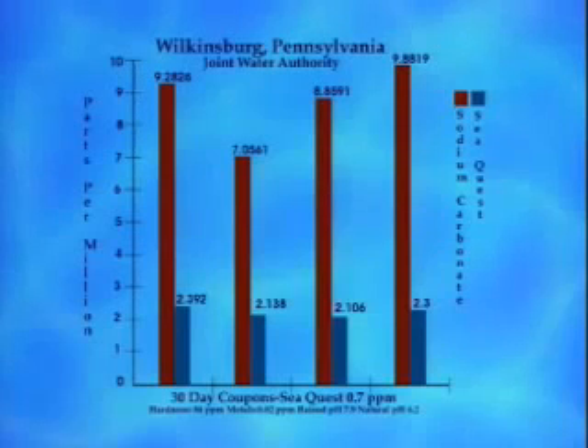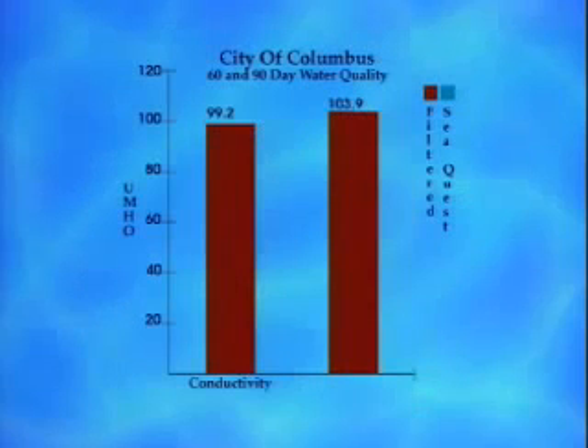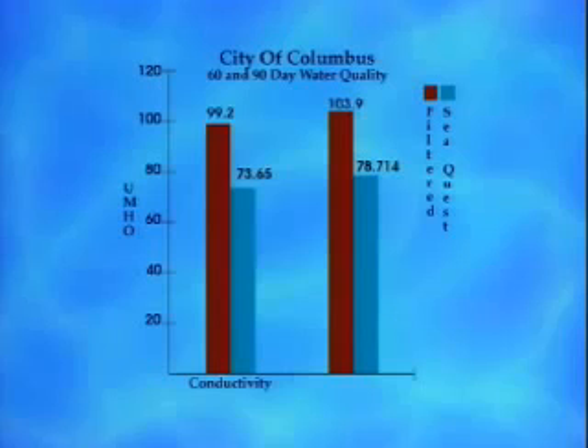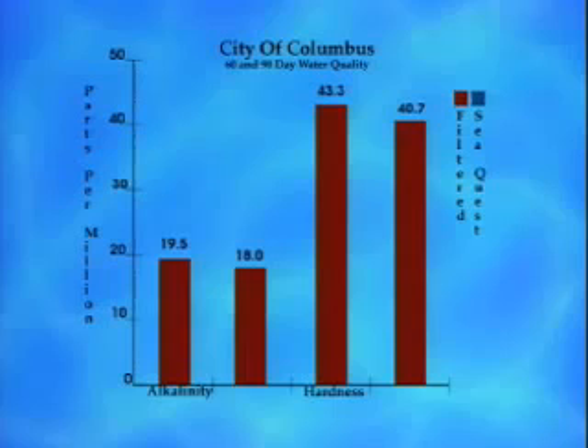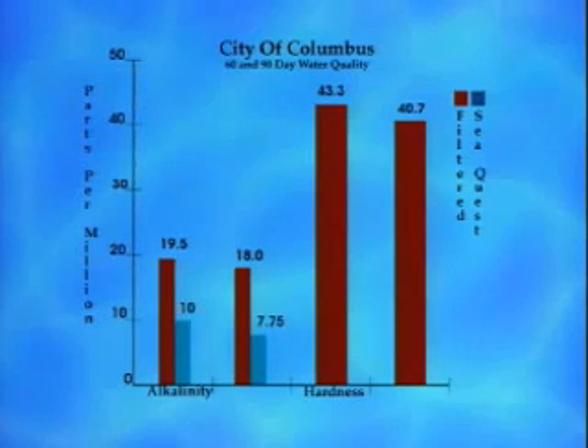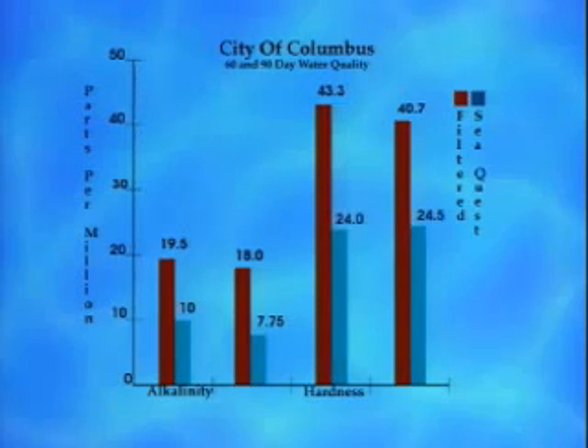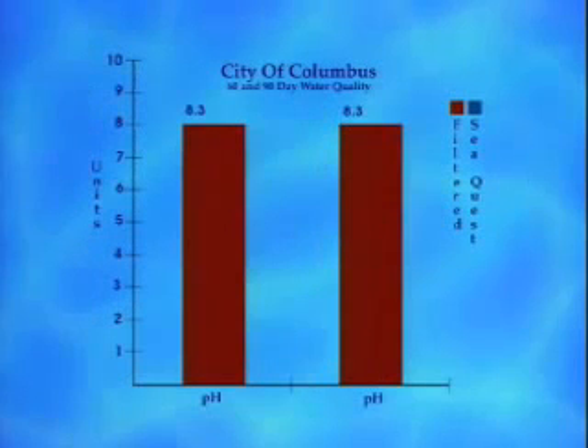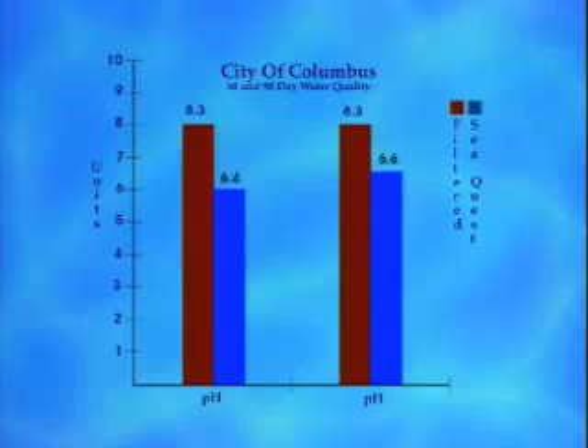This chart shows the direct effect that Seaquest has over corrosion control when put against pH control at a theoretical 0 on the Langelier index versus Seaquest on the corrosive side of the Langelier index. Here, we can watch as we reduce the conductivity of the water by eliminating the lime added into the water on the Seaquest treated side from the desired level of 100 to the low 70s. Then, we see the same happen on the alkalinity, from the desired level of close to 20 to below 10 on Seaquest. By eliminating the lime, the hardness levels dropped from the 40s to the mid-20s. The pH levels dropped from 8.3 to 6.4 to 6.6, whatever the natural pH was after filtration and flocculation.